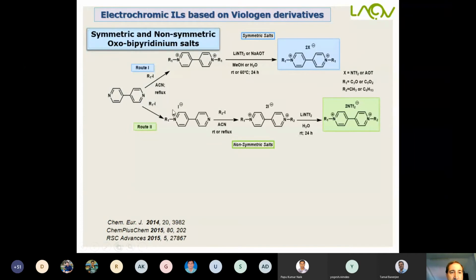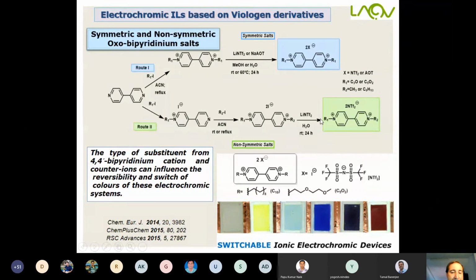It's possible also to use oxo-bipyridinium salts. For example, using oxo substituents, the type of the substituent on the bipyridinium cation and the counterion influence the reversibility and the switch of colors of these electrochromic systems. It's possible as switchable ionic electrochromic devices, and it's possible to change the coloration. Normally, using the conventional bipyridinium systems, the change is from transparent to blue. And here it's possible to change the coloration, and this can be of interest for different applications.